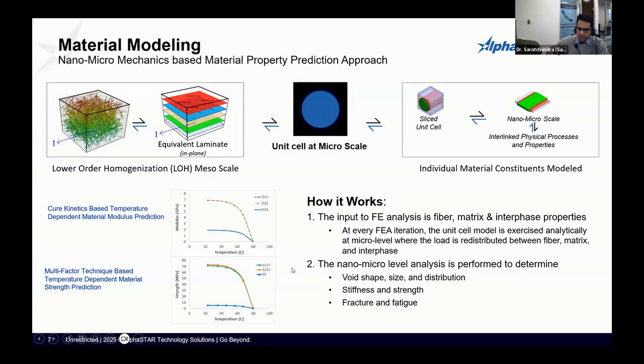And then in addition, we can also use our Cure Kinetics module to predict temperature dependent modulus and a multi-factor technique to predict temperature dependent strength in multiple directions to capture the entire anisotropic behavior.